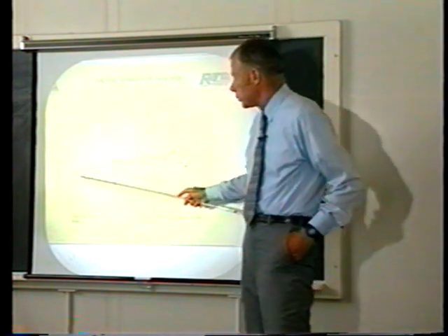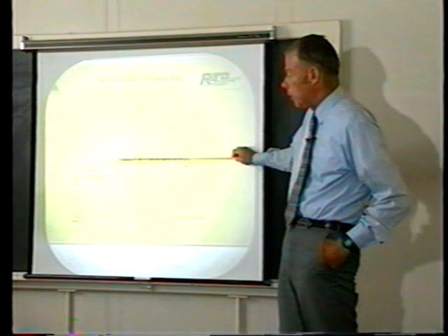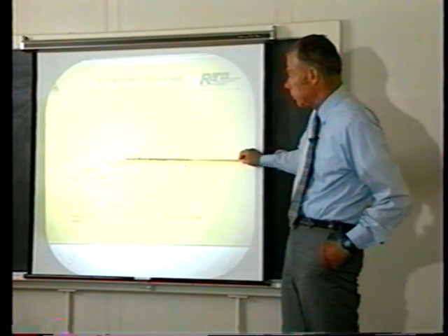After about a week of electrolysis, we see some excess heat effect here. But particularly during the last half of the experiment, there was more or less a steady excess heat effect averaging out at about 100 milliwatts of excess power. So a rather steady excess heat effect throughout this period right through here.